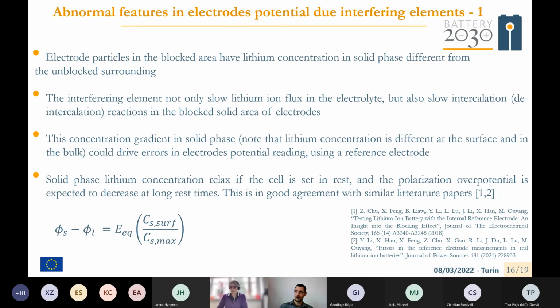So this is also a warning when you consider inserting a reference, a third electrode, inside the cell, because you can read the potential and assess the potential of single electrodes, but sometimes the fact that you have inserted something in the electrolyte domain can induce self-error in the reading of the potential of the electrode. So maybe your readings can be not completely accurate, especially if you perform a measurement of potential during cell cycling.